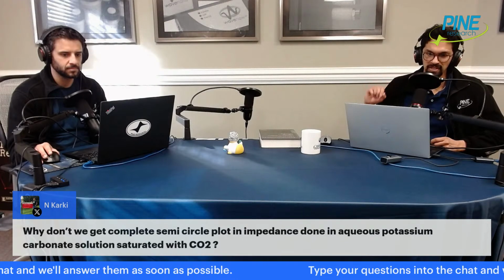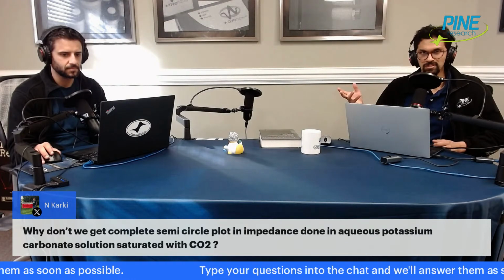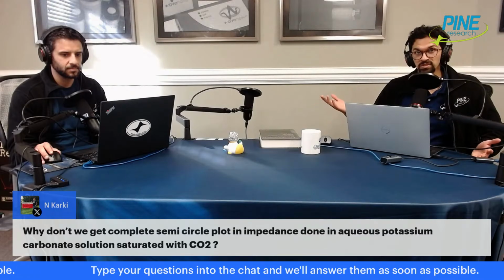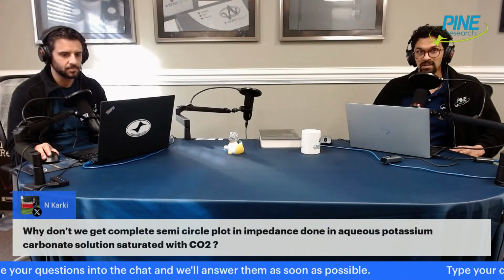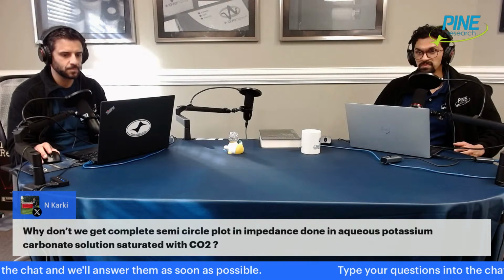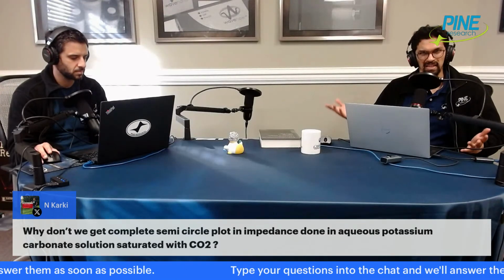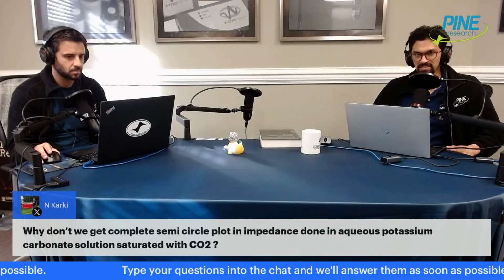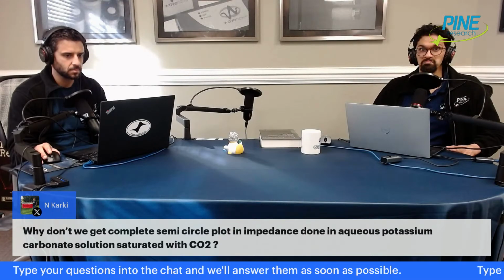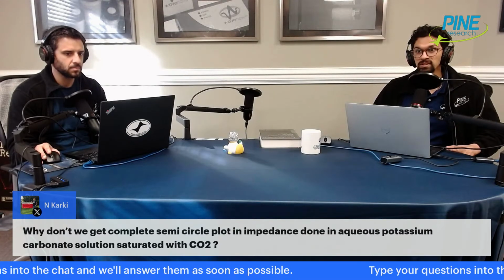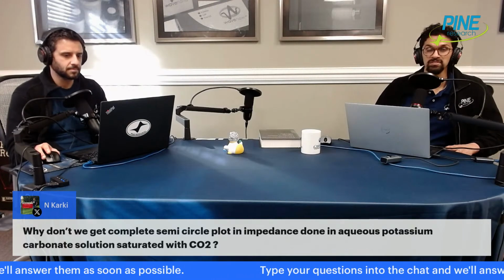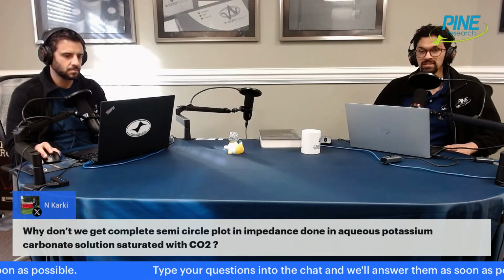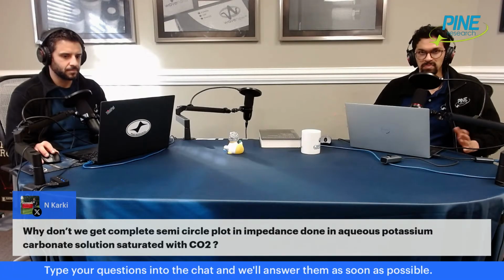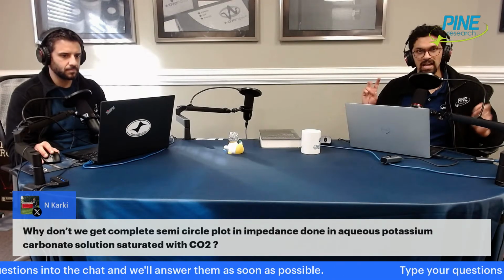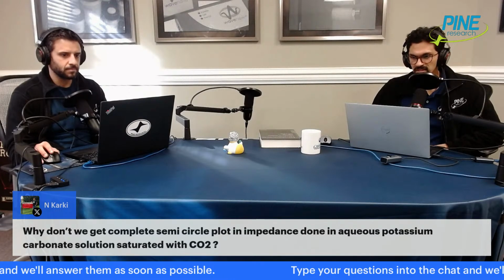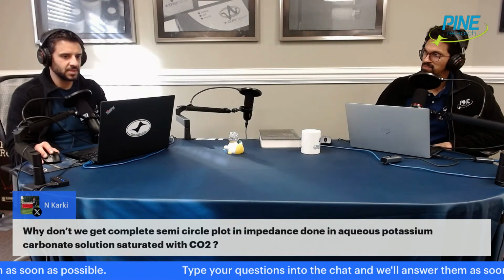If you're not getting a complete semicircle, we would need to know what the frequency range is that you're working in. Sometimes you have to go from a very fast, like 1 megahertz, not even 100 megahertz, maybe 100 kilohertz. But you may have to go to the hundreds of millihertz or tens of millihertz. If you're not going to that low of a frequency, that may be another reason, again depending on the RC time constant of your system. That's my 2 cents.